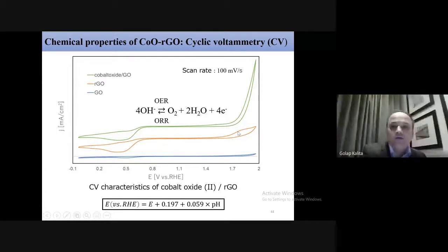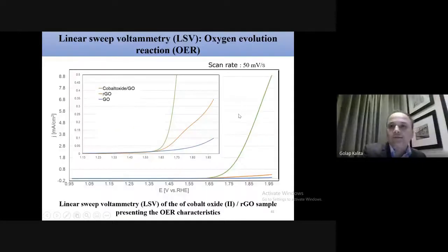But this is RGO, which is reduced graphene oxide. Here the ORR activity is good, but the OER activity is not good. So with metal incorporation, we have much better OER activity. That is CV, and we also have the LSV, linear sweep voltammetry graph. Here you see the onset potential for the cobalt oxide GO has very good OER compared to the RGO and GO. So this is quite interesting for us.